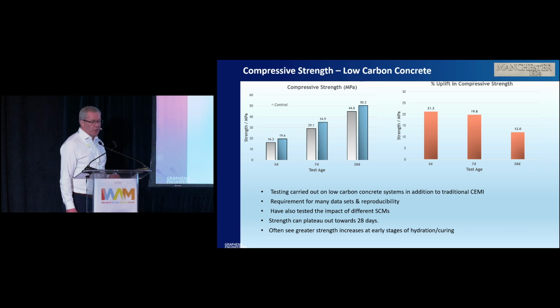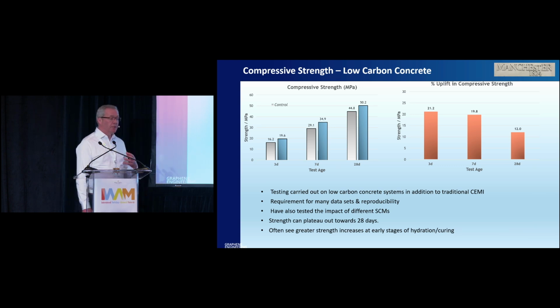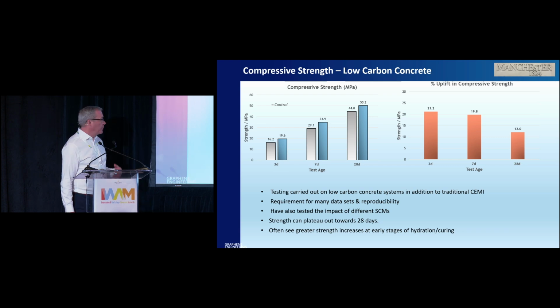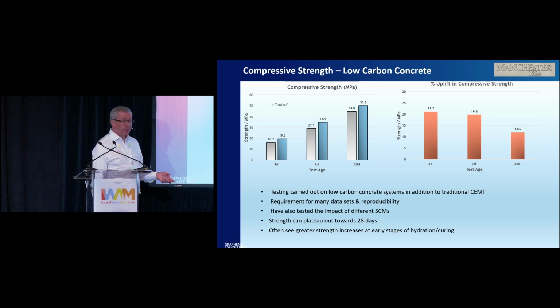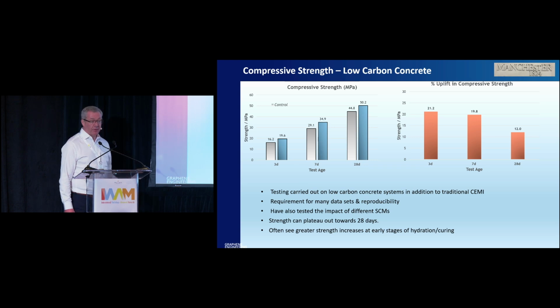If we take the cementitious system itself without graphene in, it's quite a complex system. And trying to get consistency just on normal cement, there's about a 10% variance. One of our supply chain partners, with whom we've done pours here in Abu Dhabi, but also back in the UK and in Europe, Cemex, for example, can demonstrate just by general mixing that they can get a 10% uplift in a concrete mix itself. So if you take a standard C30 mix, which is a 30 MPa mix, they can improve the strength of that concrete just by the formulation, without putting any graphene in.